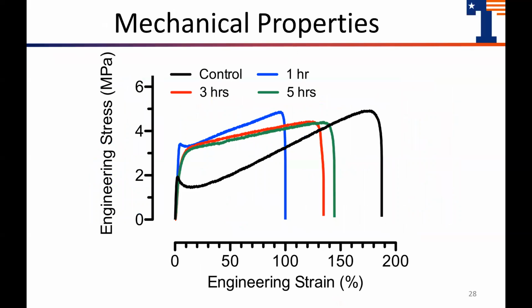So this is a stress strain graph of the PLA samples. To obtain this, the PLA samples were cut into dog bone shapes, and then they were decontaminated for 1, 3, and 5 hours. After decontamination, the samples were placed into an Instron mechanical tester, and then the stress strain data was acquired.